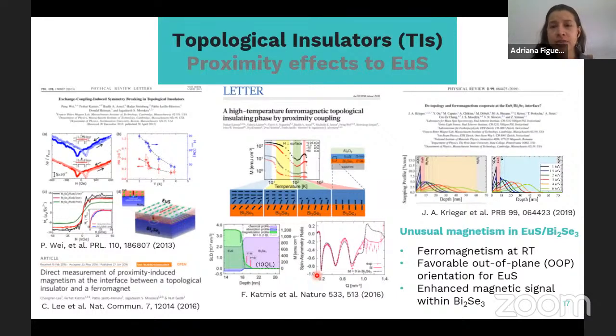And then in the case of europium sulfide, which is what I'm showing here, some reports during the past years have observed unusual magnetism at those interfaces of the europium sulfide with the TI. So even though the europium sulfide has a Curie temperature of around 15 Kelvin, some observations have shown that there is ferromagnetism at room temperature. Also, despite the fact that it has an in-plane anisotropy, some favorable out-of-plane magnetization has been observed.